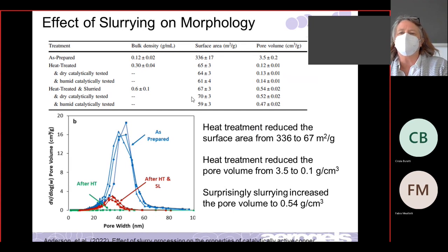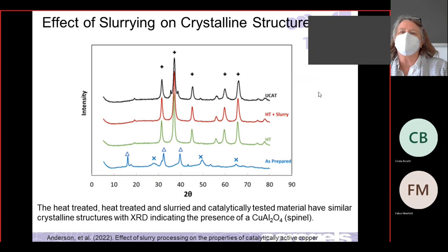Here's an X-ray diffraction pattern where it's intensity versus angle. Those peaks are related to certain structures in there. The blue is as prepared. And then as soon as we heat treat, we get these structures, and some of them are related to the gamma alumina. Others indicated that we had a copper alumina oxygen spinel, it's called.